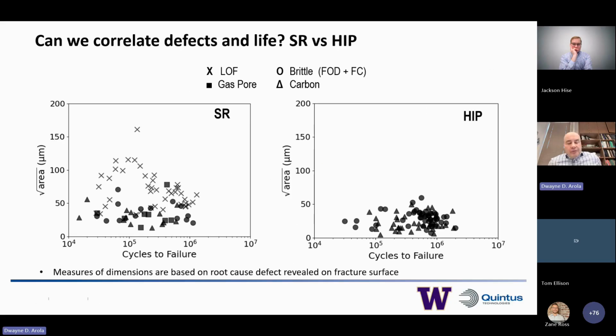All right. So for those of you that have always been looking for trends between the defects that might be present within the microstructure and the corresponding performance, in this case cycles to failure. You look on the left, we're plotting cycles to failure in terms of the Murakami dimension, square root of area. And you see in this particular case that we almost potentially see the start of a relationship between the lack of fusion and life.